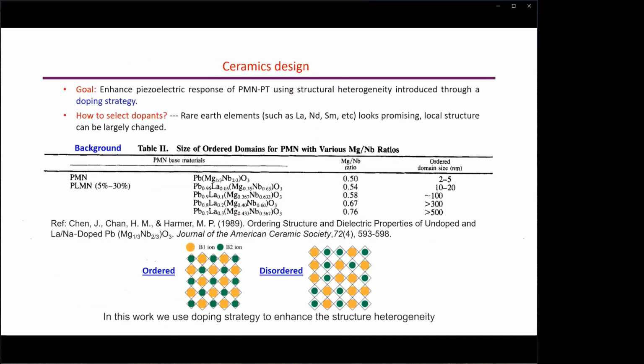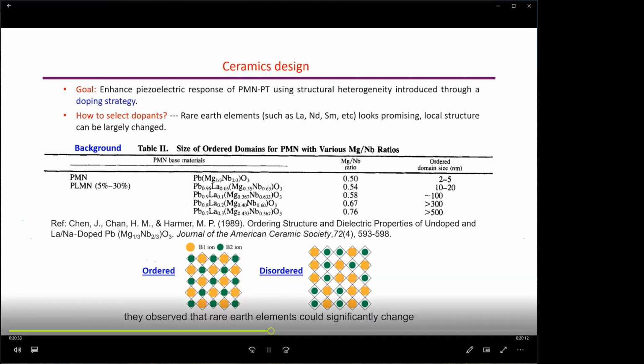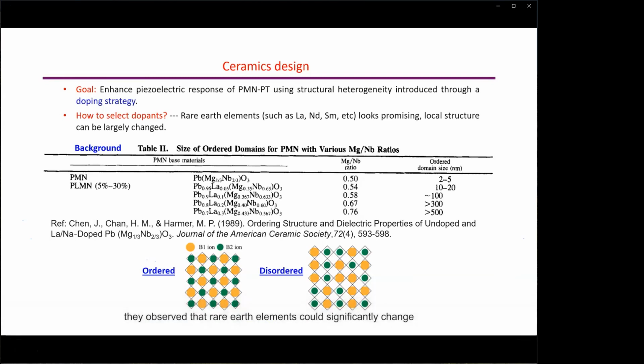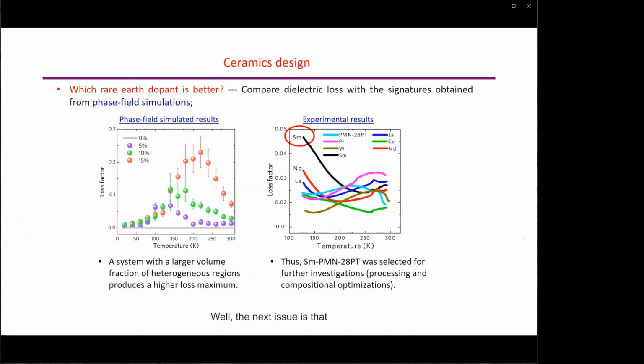In this work, we use a doping strategy to enhance the structural heterogeneity for PMN-PT ceramics. Based on TEM experiments, actually this work is quite a long time ago from Dr. Hammer's group, they observed that rare earth elements could significantly change the size of B-site cation ordered regions, as shown in this table. Therefore, we think that a rare earth element may be a good choice for modification of the local structure of PMN-PT. Well, the next issue is which rare earth element is better.